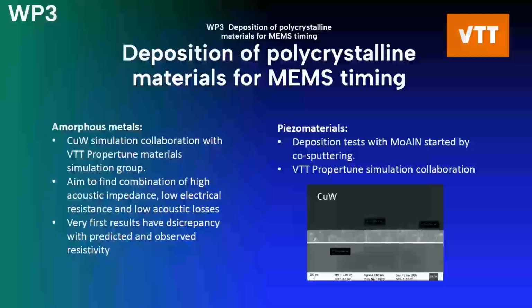In the work package 3 on the polycrystalline materials, we are studying amorphous metals with tailored properties. We have collaborated with the VTT Propertune simulation group to predict copper alloyed or doped tungsten properties, aiming to find a combination of high acoustic impedance, low electrical resistance, and low acoustic losses material. And we have done some first experiments on sputtering that yields a nice smooth film, but there is still discrepancy with the predicted and observed resistivity, but the work continues. We've also started, based on some simulation results, tests on depositing molybdenum aluminum nitride by co-sputtering. There's no results yet to share about that.